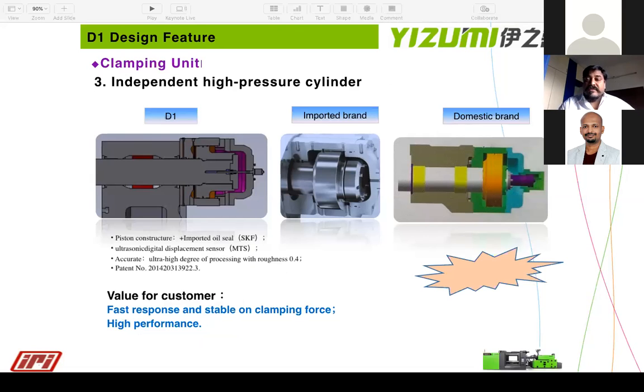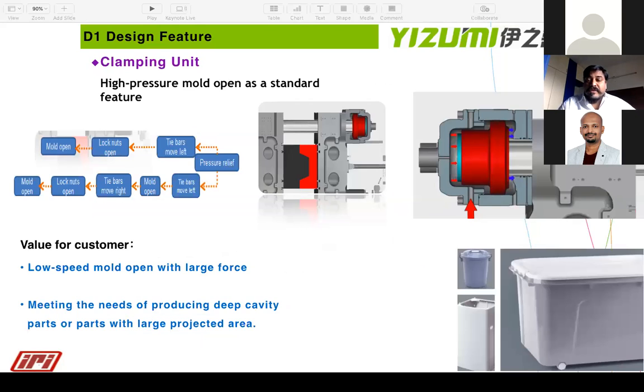So that's why the cycle time is very short in our machines, and this gives a typical advantage also, because when you have a deep cavity mold, for example dust bins or washing machine ducts, which have a lot of side cores, you need very high opening forces. That's why many times with a big toggle machine you can feel the jerk, a very high jerk, when you try to open it. But with high pressure mold opening with independent control, we have very smooth high pressure opening. So the low speed mold opening comes with very large forces. It will also increase the life of the mold as well as the life of the machines, so it's very good for deep cavity production.